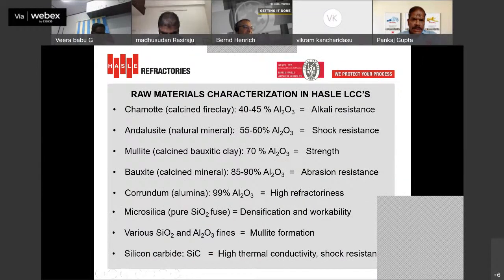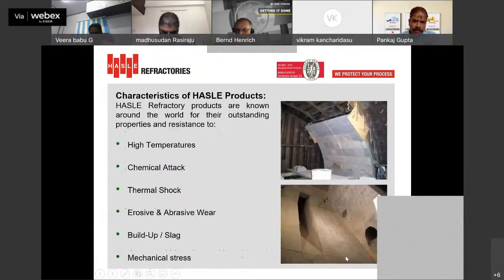To produce these products, we at Hasley prefer to go with high yield grade raw materials. We are using Chamotte for alkali resistance, andalusite for thermal shock resistance, mullite for strength, bauxite for abrasion resistance, corundum for high refractoriness, microsilica for densification and workability, and various silica and alumina fines for mullite formation. Then finally silicon carbide for high thermal conductivity, which is only used for boilers, and thermal shock resistance.